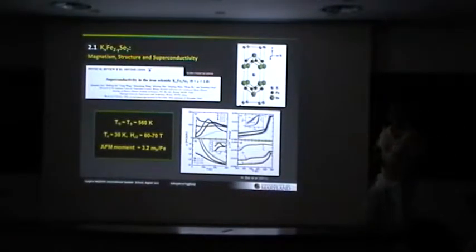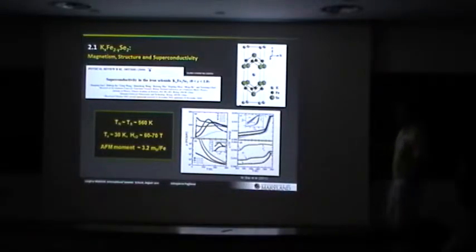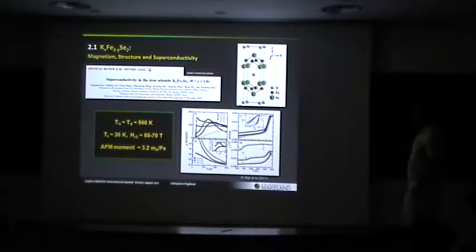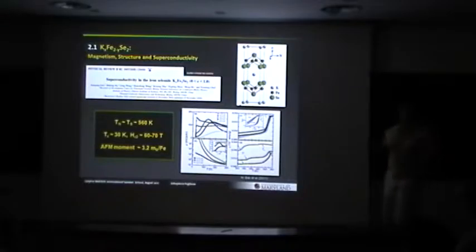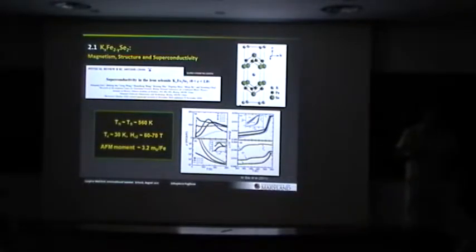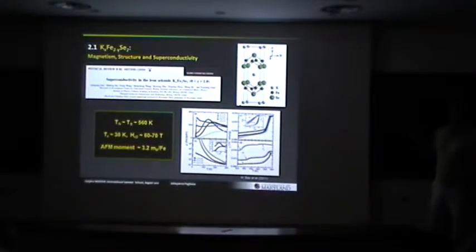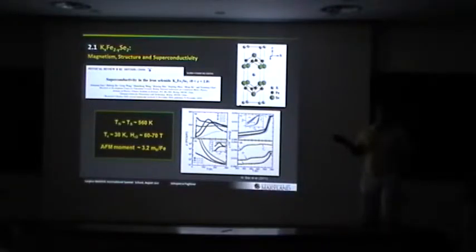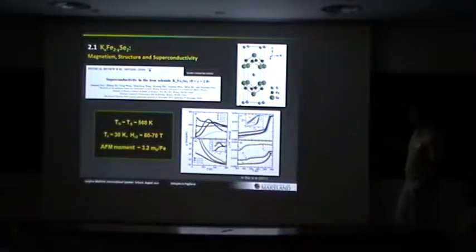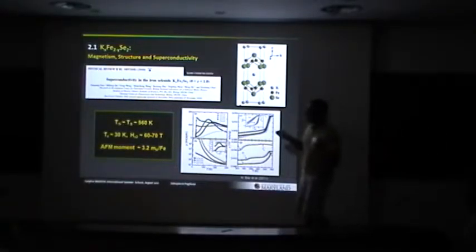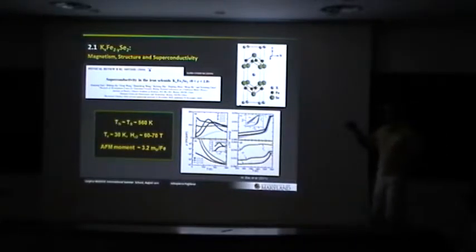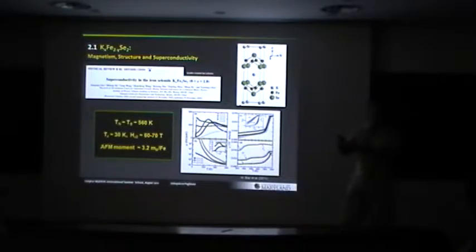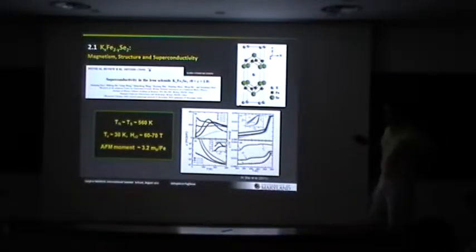Okay, so potassium X iron 2 selenium 2. This is the first report here, November 2010. So this nominally has the same so-called 1-2-2 structure, which is the thorium chromium 2 silicon 2 structure, as the iron arsenide compounds that I talked about yesterday. So, for instance, barium iron 2 arsenic 2. Instead of barium here you have potassium, and instead of arsenic you have selenium. If you just do some simple valence counting, you can see that there's something not quite right. Barium iron 2 arsenic 2 would have barium 2 plus, iron 2 plus, and arsenic 3 minus, so you get some balance there. Here you have potassium, and selenium is 2 minus. So something isn't right, and that's why you have an X here. And in fact, it turns out this 2 also isn't quite 2.